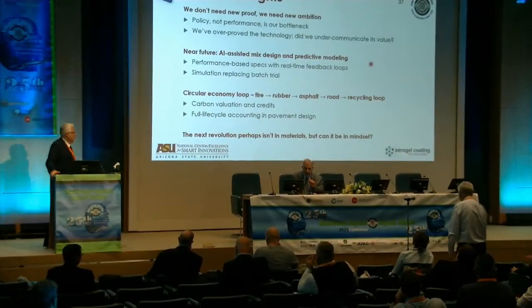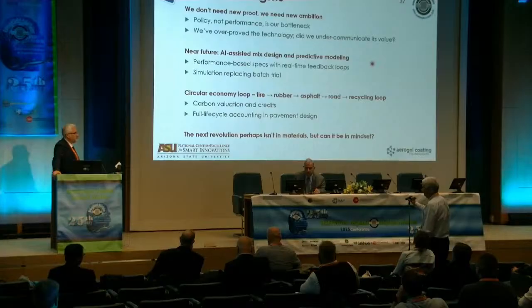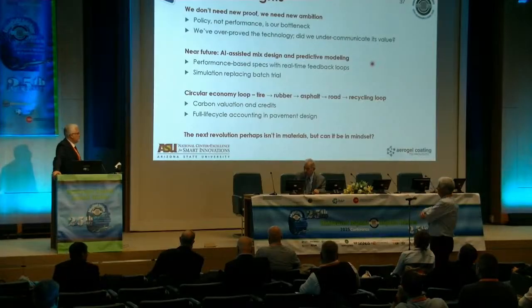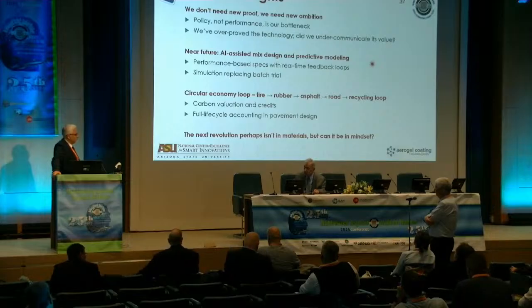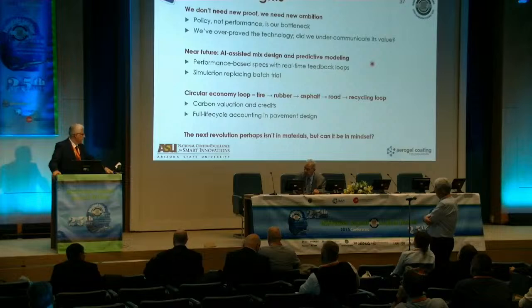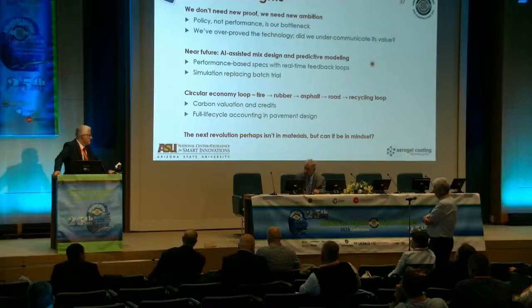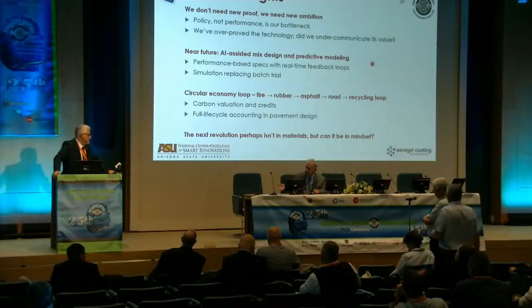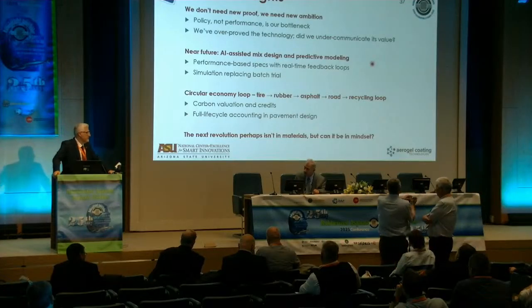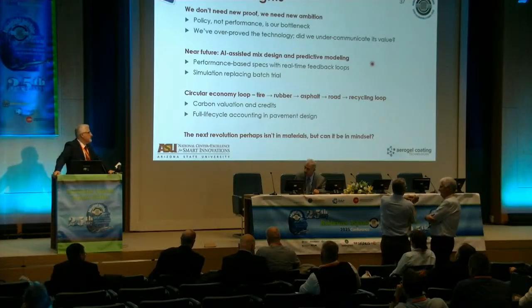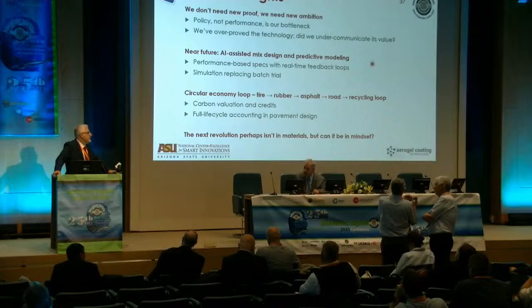So basically what you described is a thermal fatigue phenomenon. It's based on the cyclic stresses due to temperature variations. By using the aerogel, you're reducing the strains in the material because you're insulating the temperature, therefore you have a longer thermal fatigue life. Not necessarily lowering the temperature; I am reducing the temperature fluctuation.